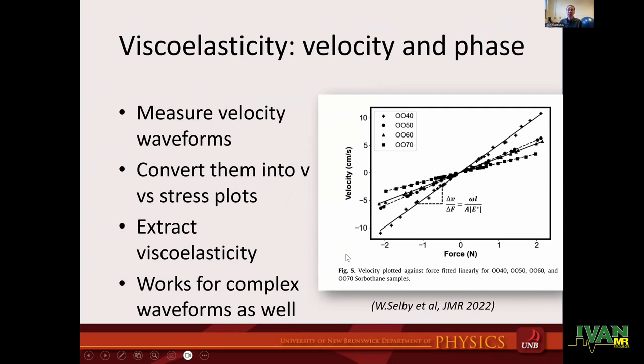So you measure the response in your sample to the applied oscillatory stress, and depending on the elasticity of the material, you will have different responses. You can convert them into your elastic modulus.